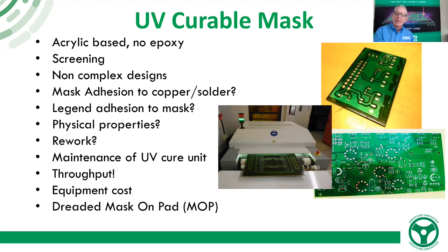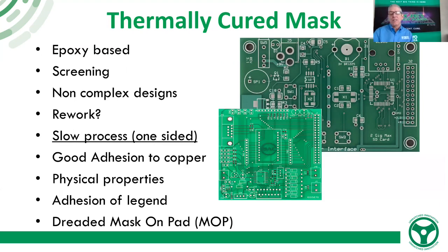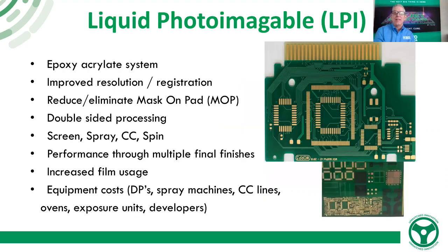And then what happened is they invented something called thermally cured solder mask. This was a huge improvement because thermally cured solder mask is based with epoxy instead of acrylates. So the physical properties were much better. The adhesion to the copper was much better. We still had to use a piece of artwork. We still had to shoot an image onto a screen. We still have to push the ink through the screen onto the board. So resolution, mask on the pads is still an issue. But what happened then, you ask? In the 80s came liquid photoimageable solder mask, or what some people call LPI.